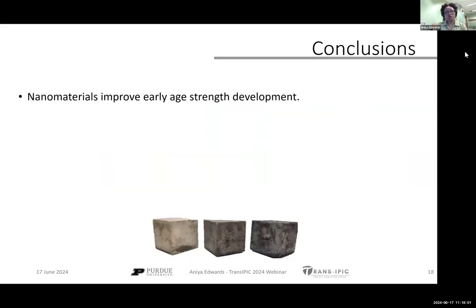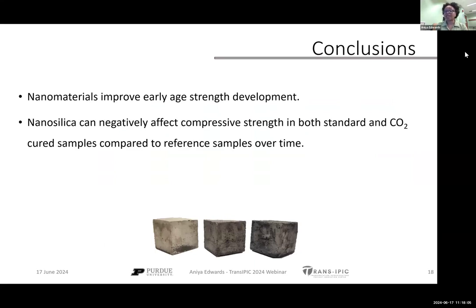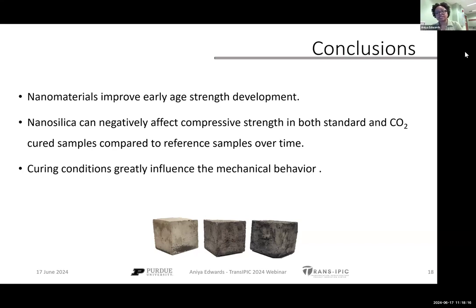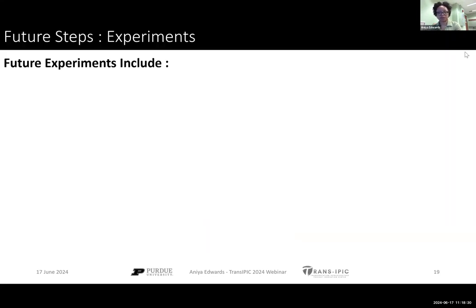So to conclude, we're seeing that nanomaterials can improve early age strength development. Nanosilica can negatively affect the compressive strength in both standard and CO2 cured samples compared to the reference samples when we're looking at time as one of our variables. And we're also looking at the curing conditions. This can greatly influence the mechanical behavior. Particularly with our nanosilica samples, we're seeing a reduction in strength for some CO2 curing and some reference samples. So the curing conditions should really be evaluated, particularly for the nanosilica.